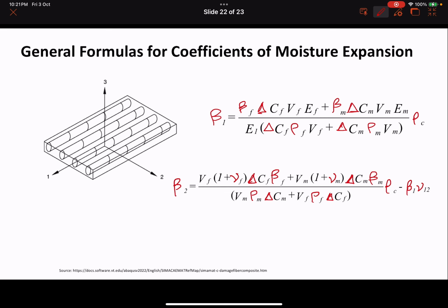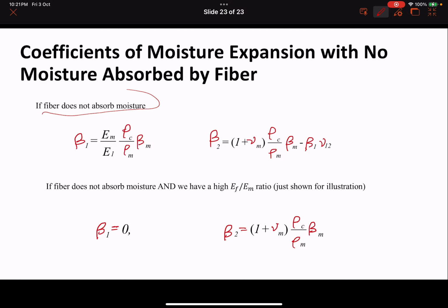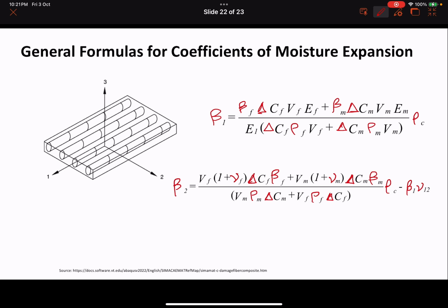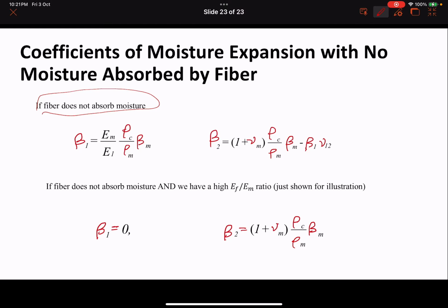But mostly because the fibers are well coated by the resin, we say that the fiber does not absorb moisture. So in that case, this very complicated equation becomes very small, because this whole term becomes 0, and then this whole term becomes 0 because the fiber doesn't get any moisture, so the weight changes nothing. And then here this term becomes 0 because del CF is 0. So you have a lot of simplification going on. So beta 1 reduces to a ratio of Young's modulus of matrix over E1, density of composite and matrix, and moisture absorbed by the matrix.